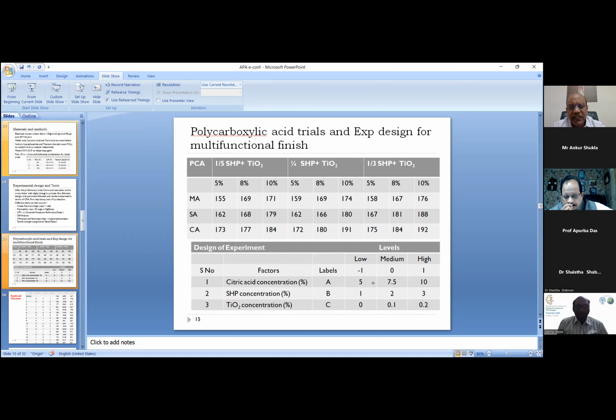So this was the design of experiment which was followed. There were three variables mainly: citric acid concentration, sodium hypophosphite concentration, and TiO2 concentration, labeled as A, B, C. This is important because later, when we go to the graphs, we'll see that these are useful while correlating the results. And three different levels: low, medium, high, -1, 0, 1, and the corresponding values. So these were taken.